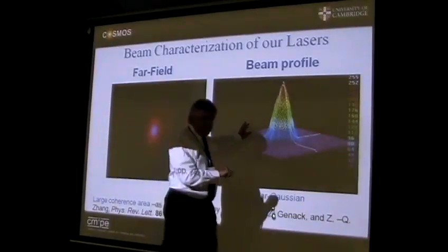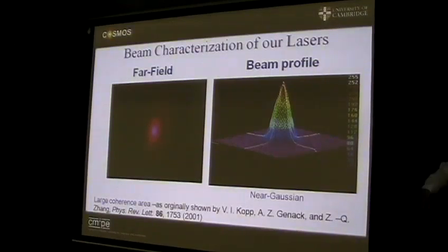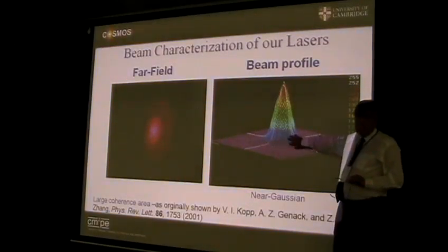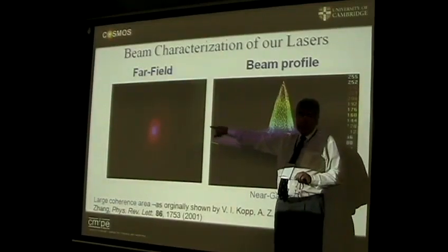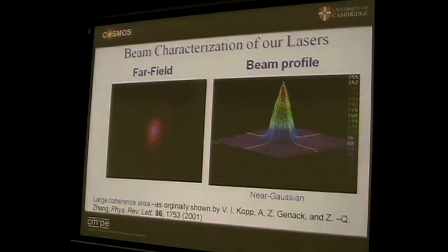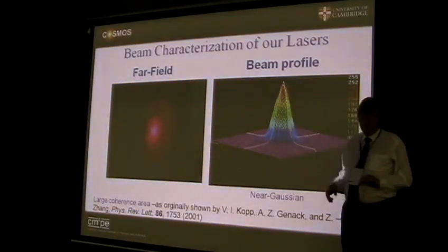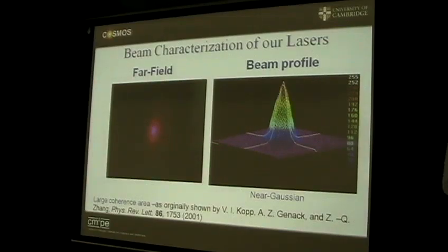That's the beam profile in the near field, close to the laser, and that's the mode coming out of the band edge. It's a single mode device. That's the far field. That's the Airy disk type in the far field. That's the mode pattern you get from these lasers. If you've got a nicely aligned sample. If you have a polydomain, then you get a number of modes, a number of lines. But with the chiral nematic, it's unlike a DFB system, and you nearly always get a Gaussian beam. It's one of the properties of the lasers themselves.